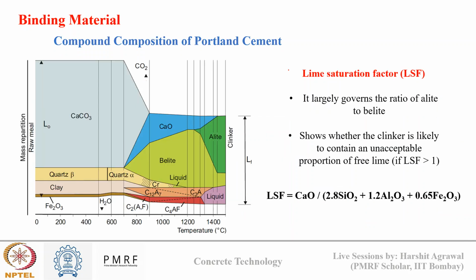So if we see the same thing of raw material and how it is changing with temperature in the kiln phase. Initially you can see we have limestone, quartz, silica, clay, alumina, and iron oxides. They are heated till 600 degrees Celsius where only moisture loss is occurring, and then beyond 600 there will be some phase changes also, like quartz can convert from beta phase to alpha phase, or there will be moisture loss from the system.